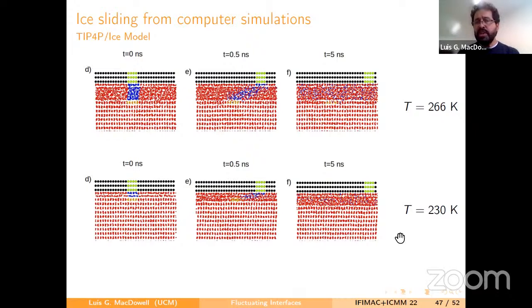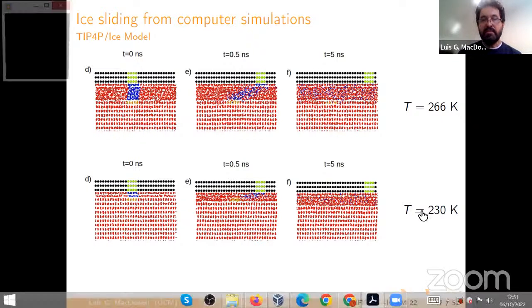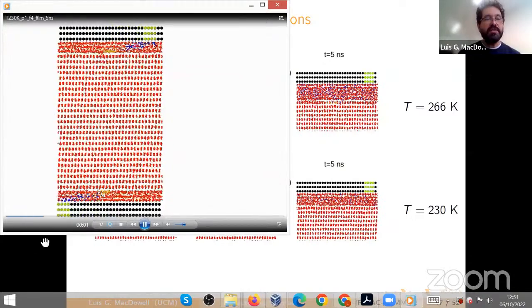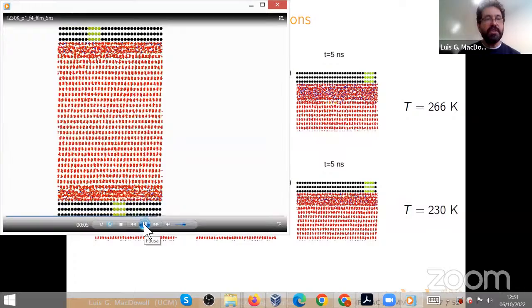Now, if we go to lower temperatures, look here. Now the pre-melting film is really very thin. That cannot do any lubrication at all. But then let's take a look at what happens. It's going too fast, I think, but let's see if it repeats again.